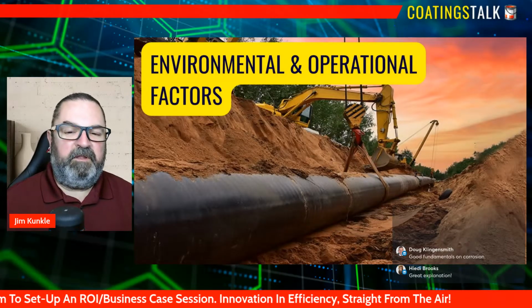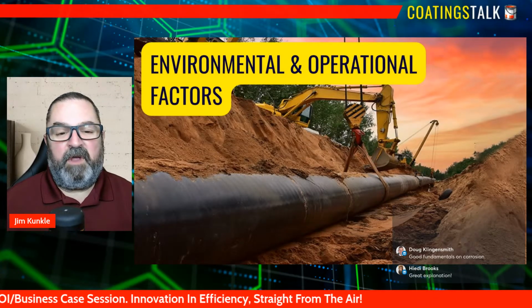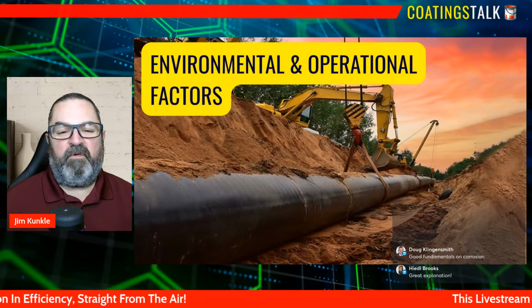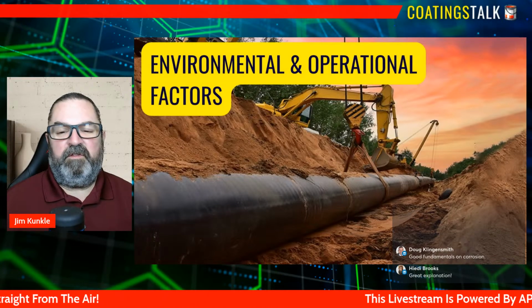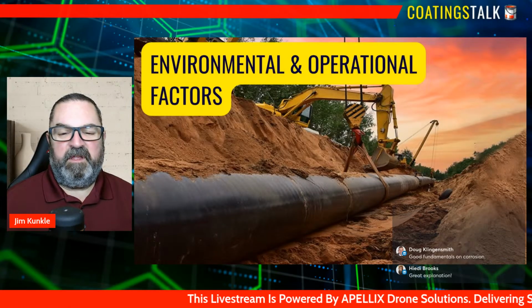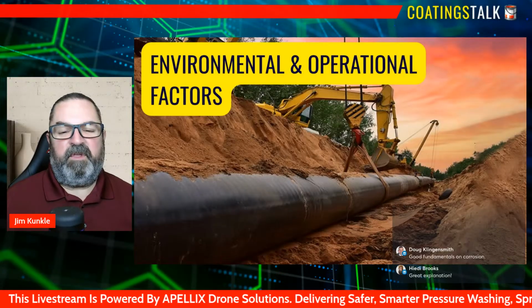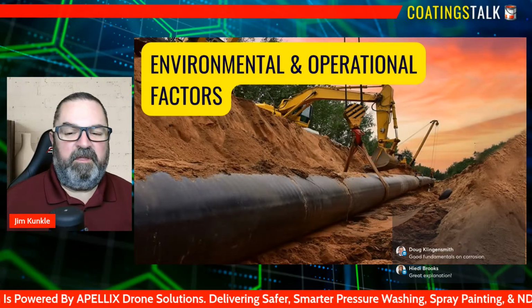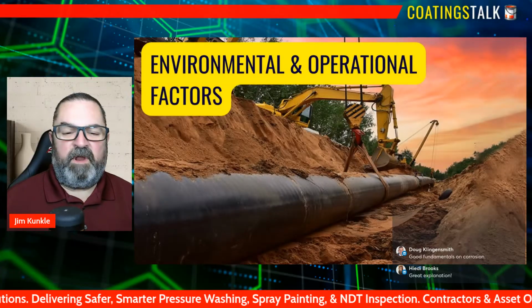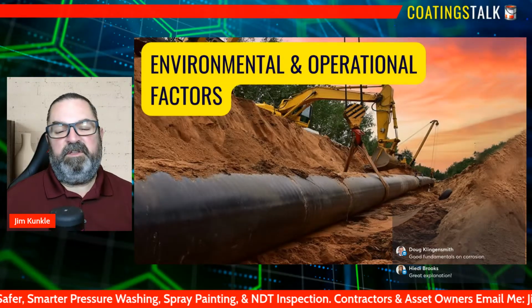Buried assets introduce a completely different set of challenges. Soil chemistry, moisture content, and oxygen availability all influence corrosion rates underground. Certain soils, such as those high in chlorides, sulfates, or organic acids, can be extremely aggressive, attacking steel even when coatings or wraps are present. Buried pipelines, tanks, and structural supports often corrode out of sight, making early detection difficult without proper monitoring systems.